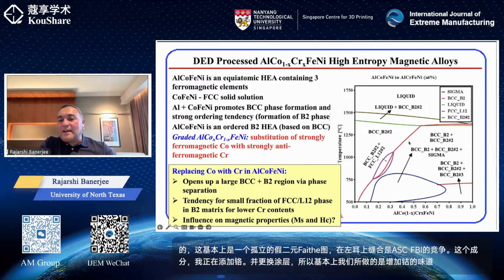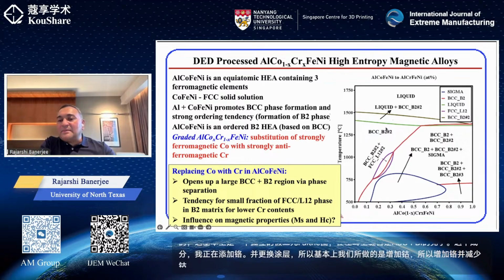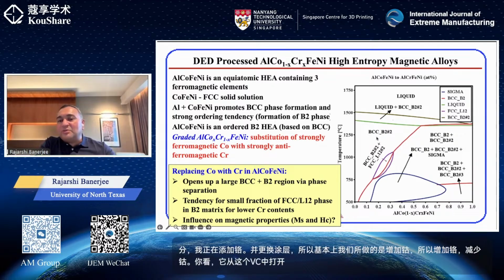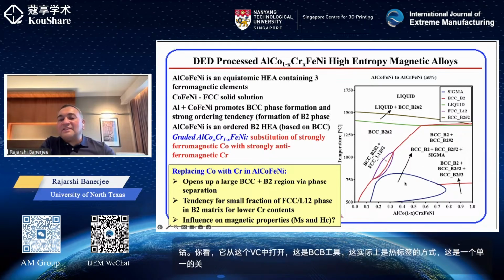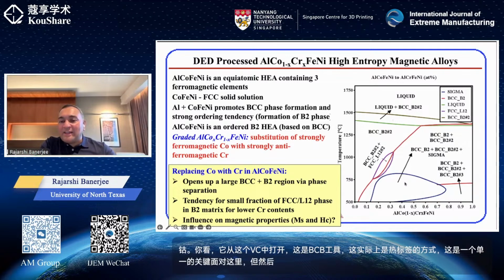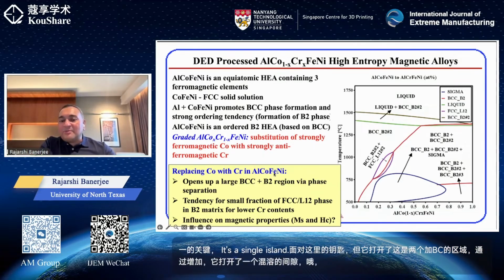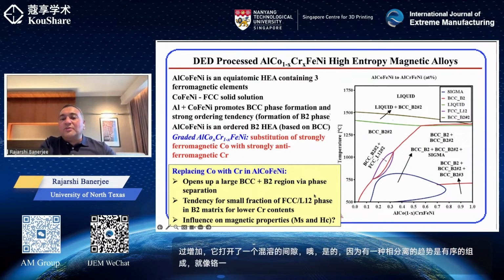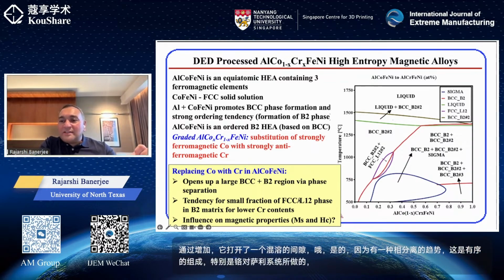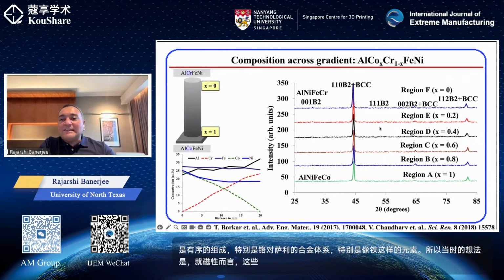You see it opens up from this BCC. This is the BCC B2 region, which is actually B2; this is the way Thermo-Calc labels it. It's a single B2 phase here, but then it opens up this B2 plus BCC region. So it's opening up a miscibility gap by adding chromium, because there's a tendency for phase separation or spinodal decomposition that chromium causes in this alloy system, especially with elements like iron. So the idea was, what are these going to do in terms of the magnetic behavior and the mechanical properties? Can it help us design for a certain range of properties that we are interested in?